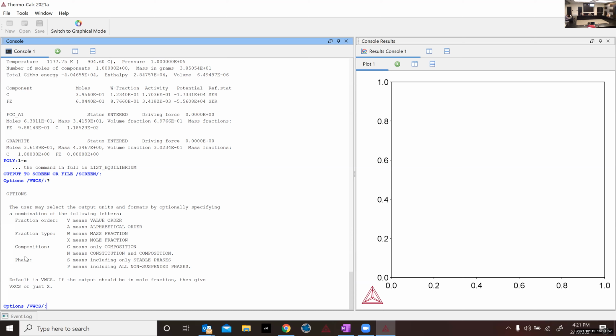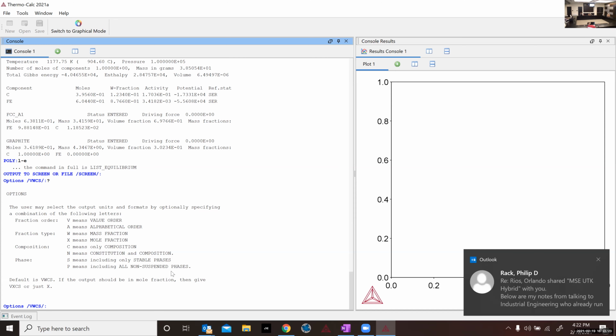And the last one is, which phases do you want to show? Do you want to show only the stable phases or all non-suspended phases? I typically don't change that. I typically just show only the stable phases. There are times where you may want to show all non-suspended phases because you may want to know what is the equilibrium composition of this phase that is unstable.